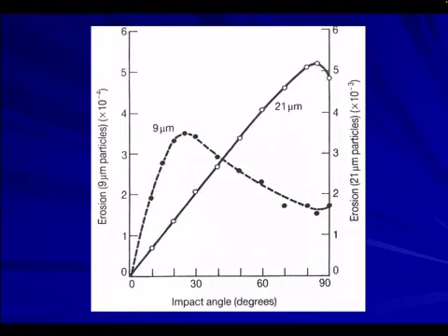And so here we see the effect of the particle size. So when the particle size is small, then the impact angle reaches a maximum just below 30 degrees, but when you have larger particles, then your impact angle is probably almost the highest at 90 degrees.